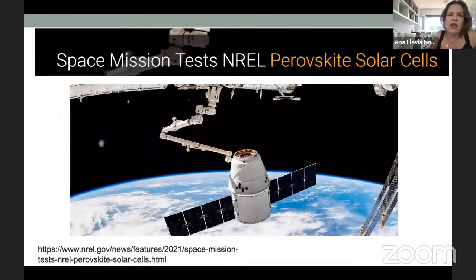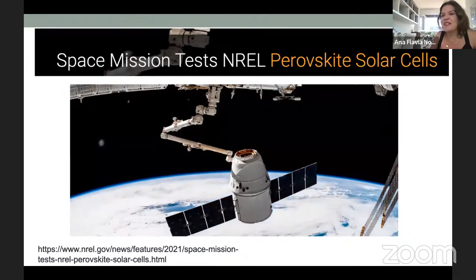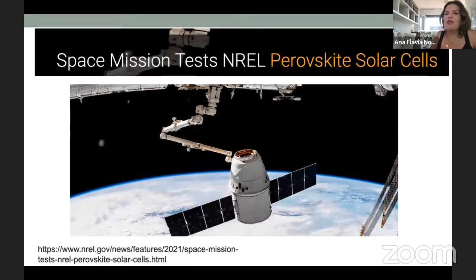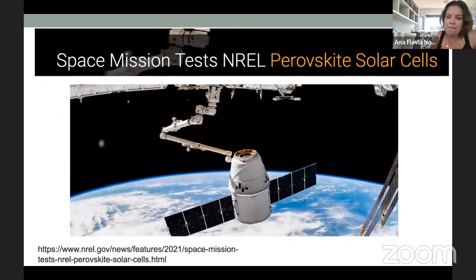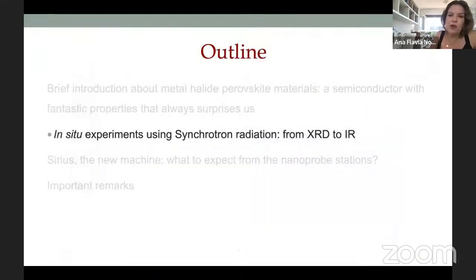And then recently, NREL also had this space mission test. NREL is testing these perovskite solar cells. It's a very interesting site to look at. They launched these perovskite solar cells to test them in space. This is interesting because in space, we just get rid of the humidity, okay? So they're expecting them to be more stable.